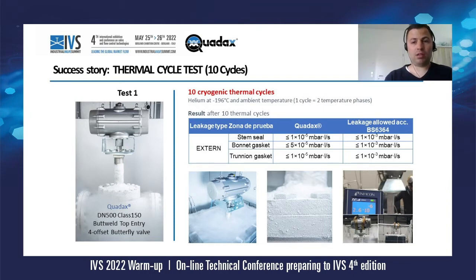And this is that Quadax really had the best values of leakage, looking on those 10 thermal cycles that we were going through from ambient to minus 196 10 times. We never exceeded those very low values that you can see here on this side. And here you see the leakage rate which was allowed. And this shows our very, very proven design of cryogenic sealing technologies.